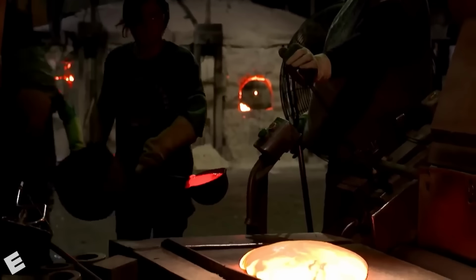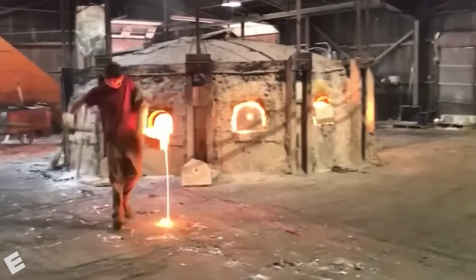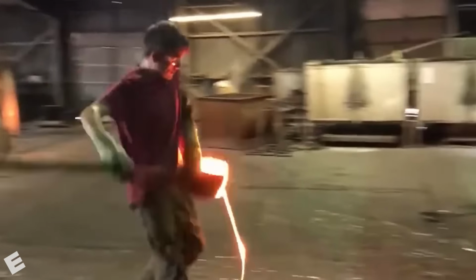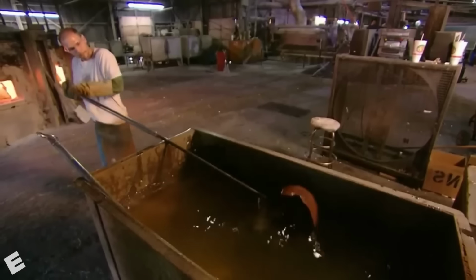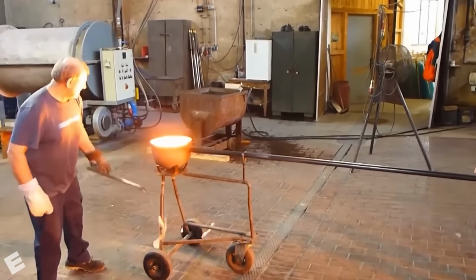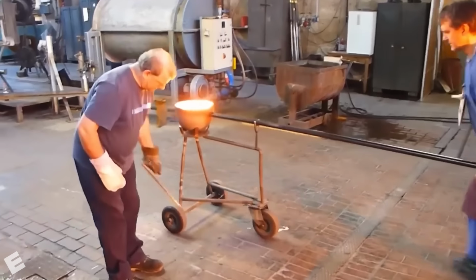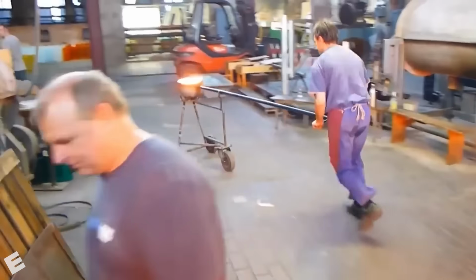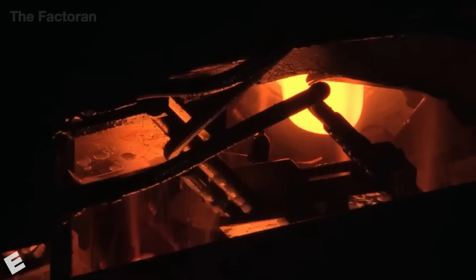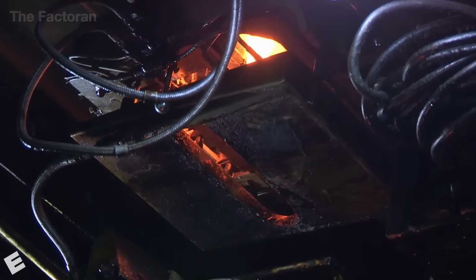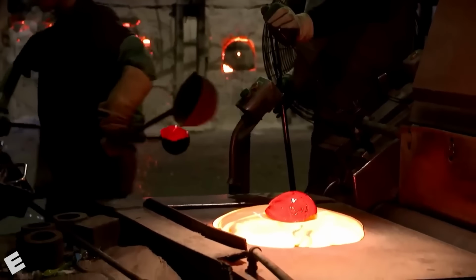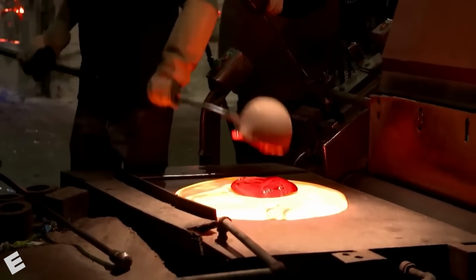The process is so fast and precise that even a slight delay can create defects, cold spots, or other imperfections in the finished glass. The metal ladles must be cooled between every use, otherwise the next batch of molten glass would stick to the surface. These ladles come in different sizes and can hold anywhere from about 4 to 40 pounds of molten glass. To create a single color, workers sometimes pour material from as many as 5 different ladles at the same time.